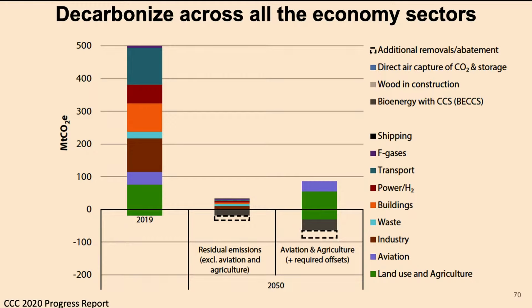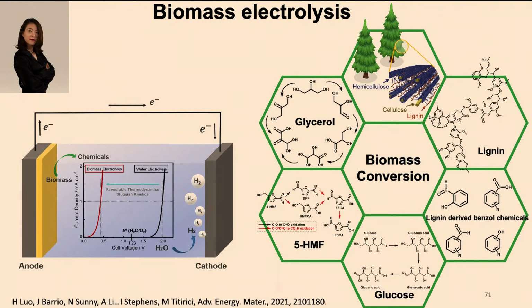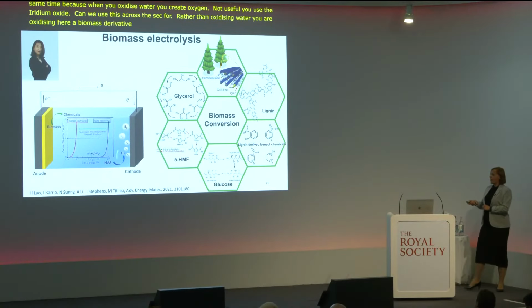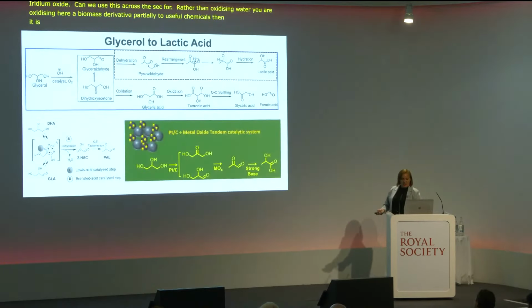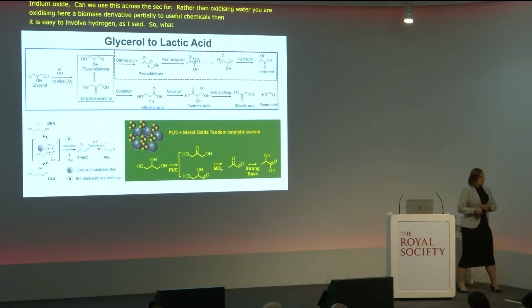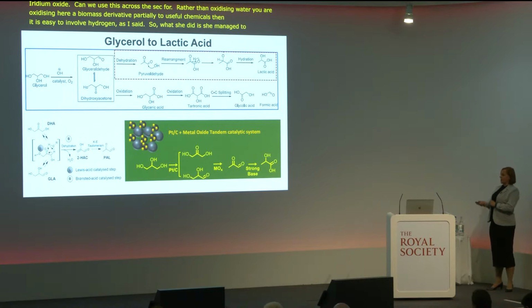Now, what we're doing in our group, and according to the UK government, is what if we make hydrogen but making something else useful at the same time? Because when you oxidize water, you create oxygen. It's not very useful. You use iridium oxide. So can we actually decarbonize across the sector? And that's where another of my amazing postdocs, Hui, is working, and she's working on biomass electrolysis. So rather than oxidizing water, you oxidize a biomass derivative, whatever it is, partially oxidize it to some very useful chemicals, and then it's easy to evolve hydrogen, as I said. And so what she did is she managed to actually produce green hydrogen and green plastic at the same time.